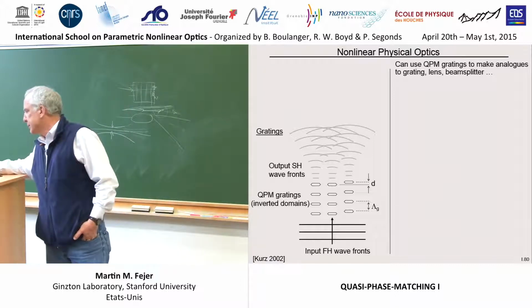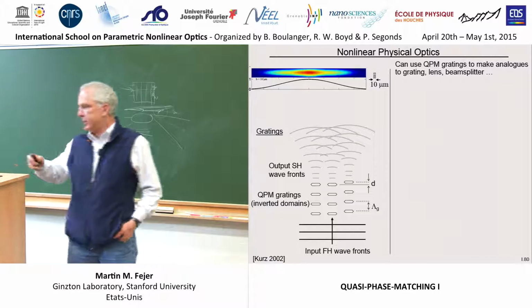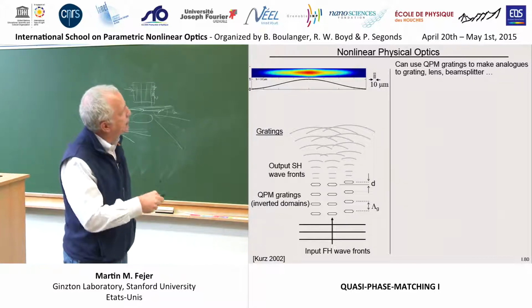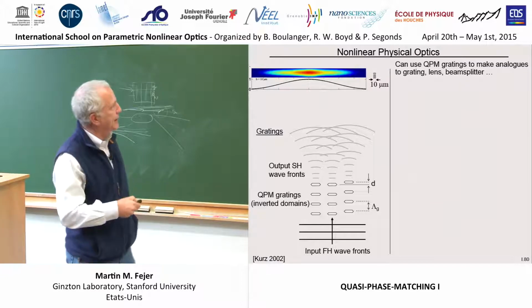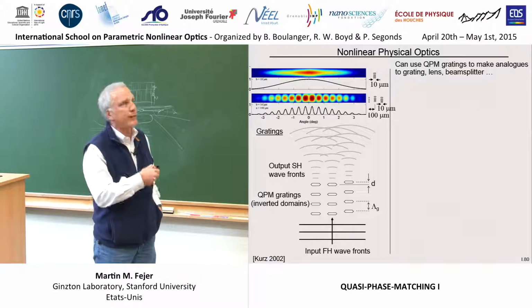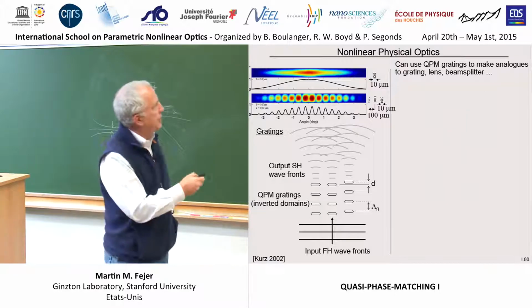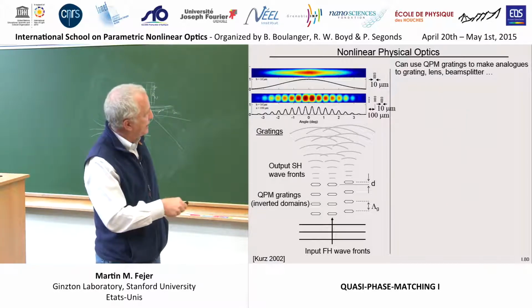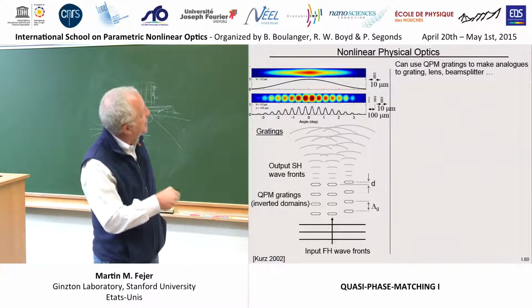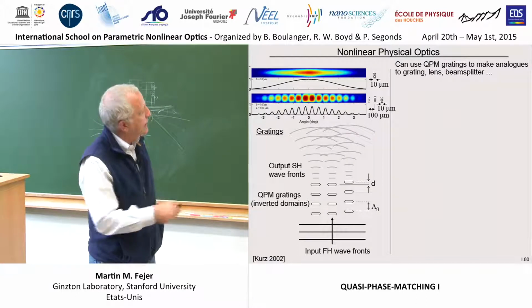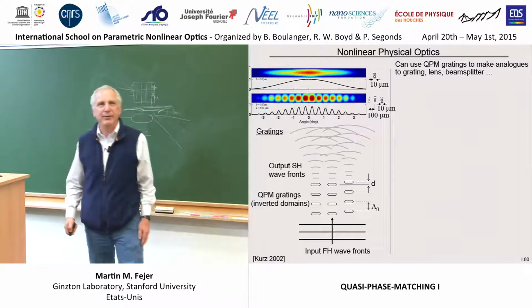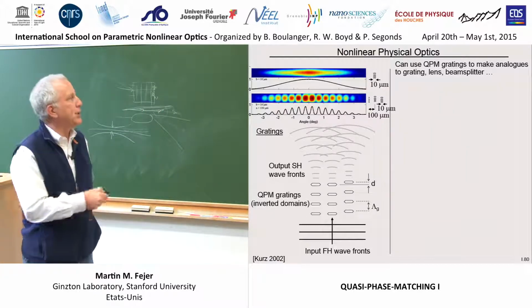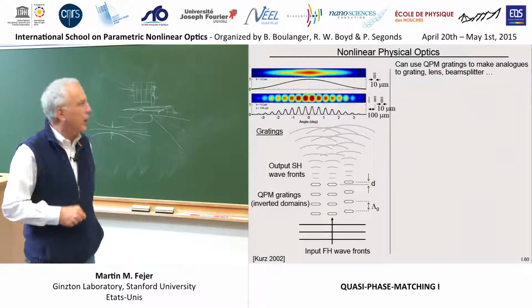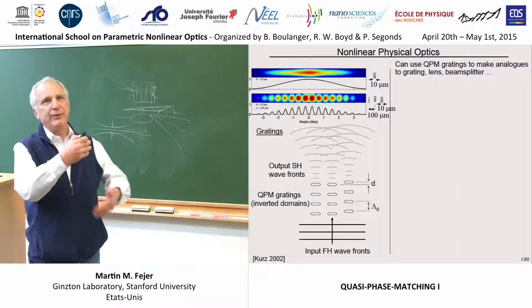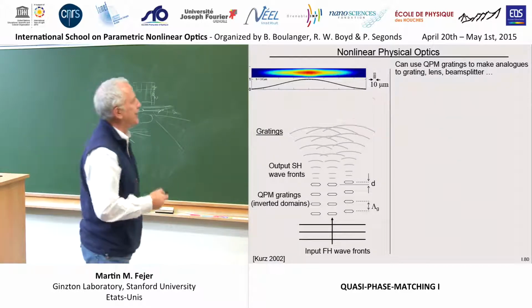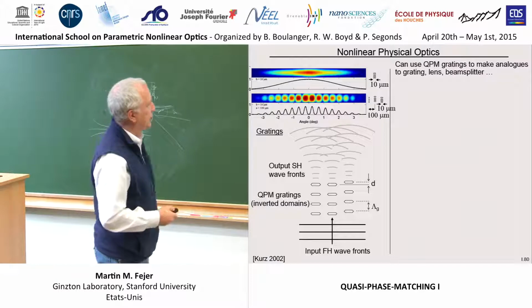And if you take a single stripe, what you see is something akin to the diffraction pattern of a 10 micron wide slit, except this is the second harmonic we're measuring in the far field here. If you now illuminate, I believe it was 10, a pattern containing 10 of these strips, you can see what looks exactly like the multi-slit diffraction pattern of 10 things. But this is a fully nonlinear process. There's no modification of the linear properties at all here. All that's modified is the sign and position of the chi2s. So it's a fully nonlinear version of a simple physical optic device.